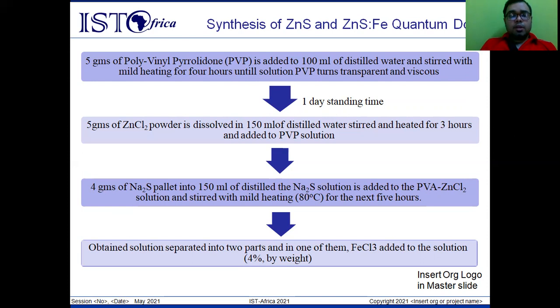So we prepare a PVP solution, give it a one day standing time, and to that we add zinc chloride, and then we add sodium sulfide. This zinc chloride and sodium sulfide react together to form ZnS quantum dots, while the other byproducts are water soluble, so they can be easily separated and washed away. And for doping purposes, we add 4% by weight, a very trace amount, of iron chloride, FeCl3, where the iron ion acts as a dopant.